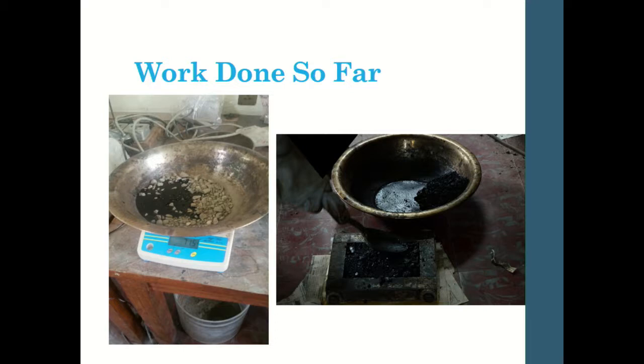Right. So to make a sample, I am required to heat asphalt and the stones. These stones are actually different size fractions, and it's a mixture of crushed gravel, sand, and filler. I mix it with a certain asphalt content and ensure that it is mixed to maximum distribution. Once I have achieved that, I place it in this mold and ensure that all the corners are filled so I can get a uniform shape.